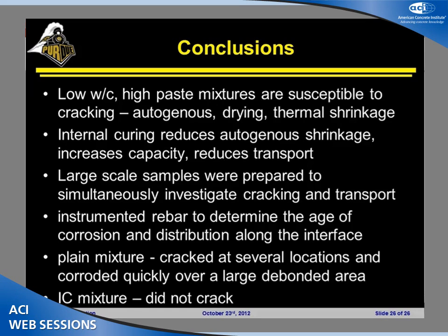Any other questions? One last question. I'm trying to understand creep and modulus at very early ages. At what age do creep and modulus actually show a difference, or a significant difference, in a high-strength mix compared to a normal mix? Oh, well, the differences are sort of built into the system. If you're comparing a 30 MPa mix with 100 MPa, you've got different moduli from very early on because you've got more of the system that's dense, more of it's hydrating, so the modulus is very different at those early ages.